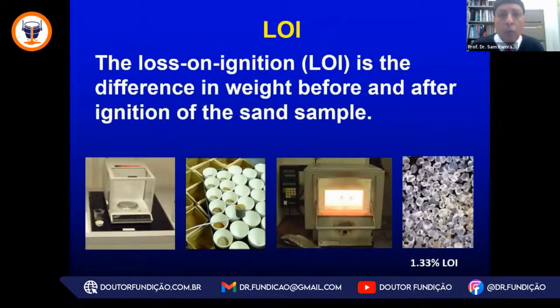So after we have tested a dish-shaped specimen, we can collect the residual for use in the loss on ignition test. And this is where we take that specimen and we take the weight before ignition and after ignition. The range of the mass change divided by the original mass brought to a percent is an indication of the LOI. And after the LOI, silica sand appears snow white after we have burnt off the binder.